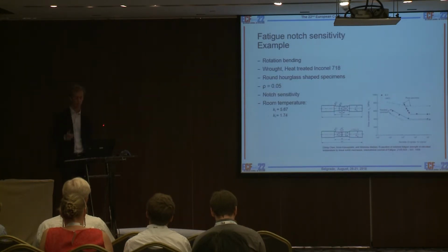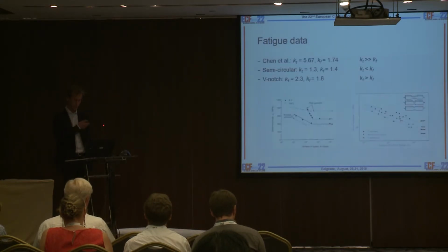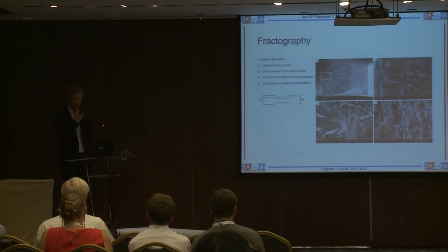And if we look at the fatigue notch sensitivity for wrought Inconel from a paper by Nisitani, we see that the elastic stress concentration is a lot higher than the fatigue reduction factor. Comparing this, we see that the semicircular one has the higher fatigue reduction factor. So we went to fractography by SEM.